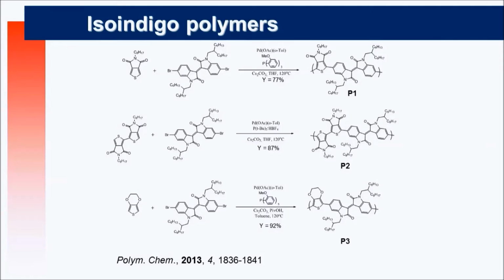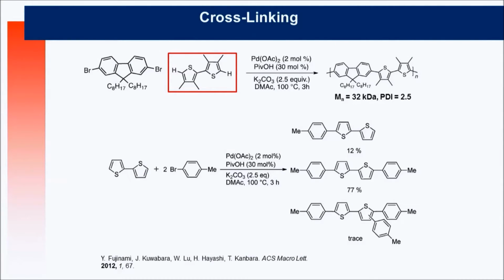We also tried with the isoindigo comonomer, and we got good molecular weight, something comparable to what you would get from Suzuki coupling, for instance. Problems. That was a nightmare for us. If you want to copolymerize fluorenes and bithiophenes, and bithiophene is a very important unit in the field, you get insoluble materials. The reason is that there are some traces of what we call branching. So the selectivity is not perfect, and branching will cause cross-linking, and cross-linked materials are not soluble anymore. So a little branching will become cross-linking, and processing will disappear.